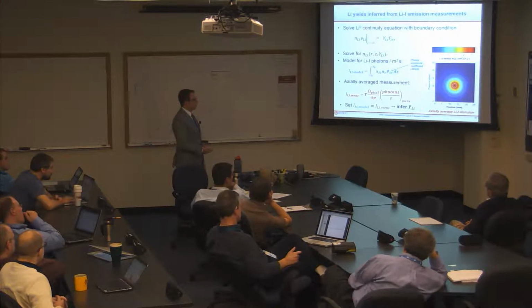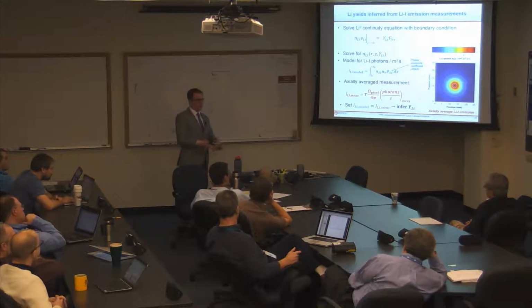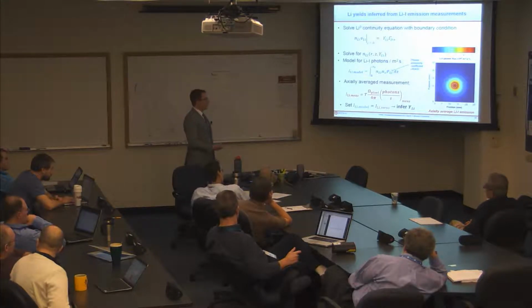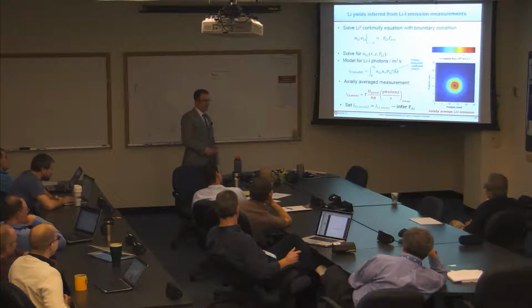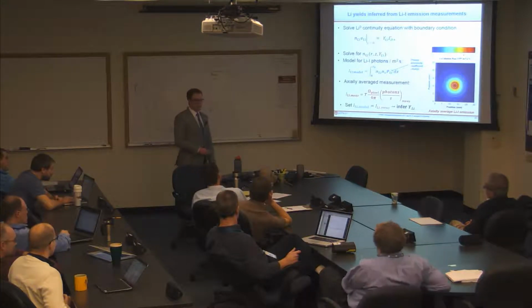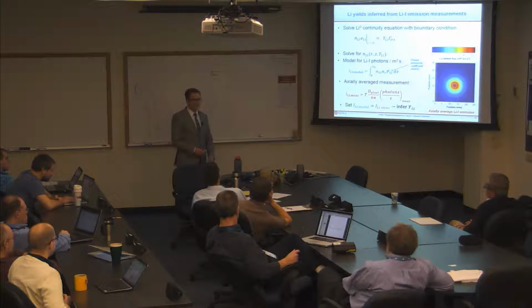No, the only thing I did here was correct for the tilted line of sight. The camera's tilted at about a 45-degree angle, so I corrected for that. But this was for a thin lithium layer, something that was initially 200 nanometers. So no melt motion there.